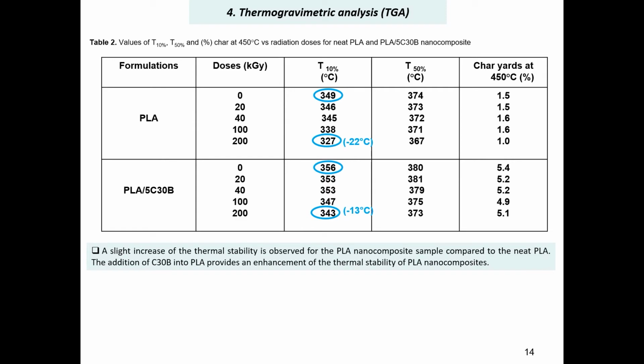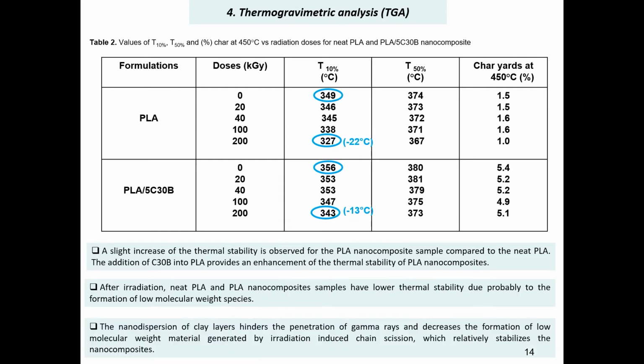The thermal stability of the samples also was analyzed by TGA, and table 2 summarizes the main results through the values of T10, T50, and the percent of char recorded at 450 degrees C versus radiation doses. And it is clearly shown that a slight increase of the thermal stability is observed for the PLA nanocomposite sample compared to the neat PLA, which means that the addition of the C30B into PLA provides an enhancement of the thermal stability of PLA nanocomposites.